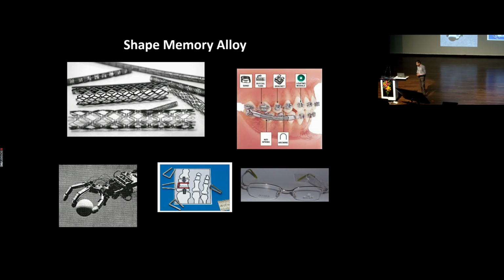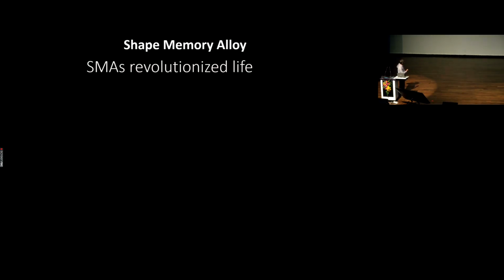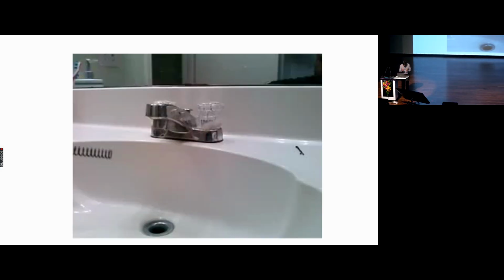And in fact, the best way to illustrate this spectacular property would be what I show in the next slide, which is called shape memory alloy, and why it has such beautiful behavior. What we are going to show is that this little spring that you're seeing over here is made from the shape memory alloy. It's given this particular spiral shape at a high temperature, and then at room temperature, where it has actually a crystallographic transition that you don't perceive by looking at the shape, at that low temperature, it can be deformed. And it is deformed, and as I'll show you now,